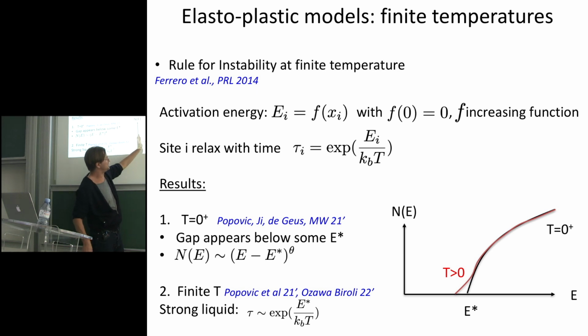Effectively, what it does is creating some absorbing condition. Those regions are dead regions. As soon as you enter one, you will die. And here is our absorbing condition. Close to the absorbing condition, we have the same physics as before, and so we have this exponent theta.